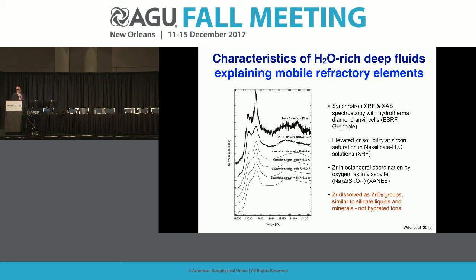So here we have results from some synchrotron X-ray spectroscopy work that we've done. I won't go into this in any detail, but the peaks that you see in zircon-saturated fluids indicate site similarities to site environments that you find in various zirconium minerals. These are oxygen-coordinated sites. The zirconium is going into the solution not as a charged cation or as a hydroxide species, but as something that's participating in these polymeric types of solute structures.